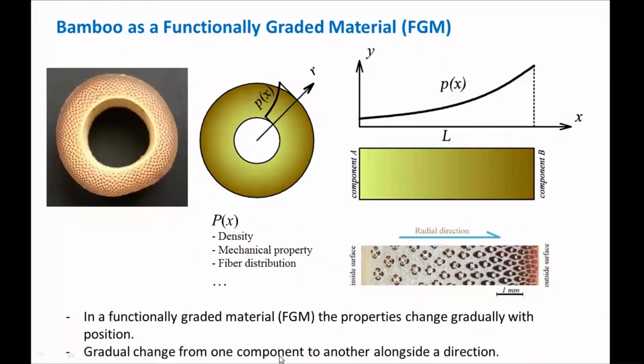In a functionally graded material, or FGM, the property changes gradually with position. You can define it as a gradual change from one component to another alongside a special direction, that you can see in the radial direction. Component A gradually becomes component B, and you can see exactly it happens here. You have more matrix here and less fiber, and here you can see more fibers and less matrix or less parenchyma.